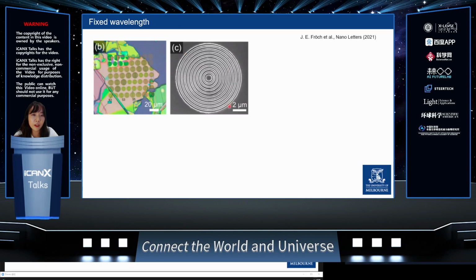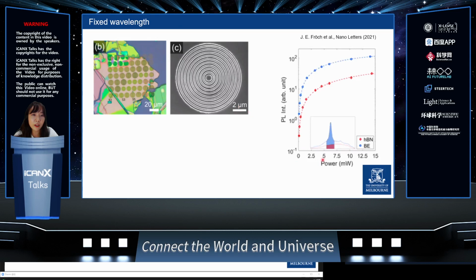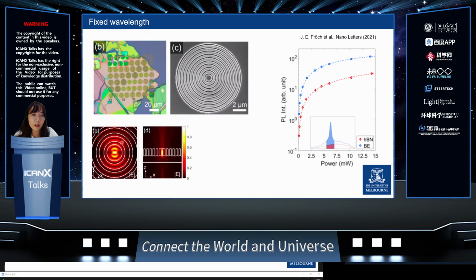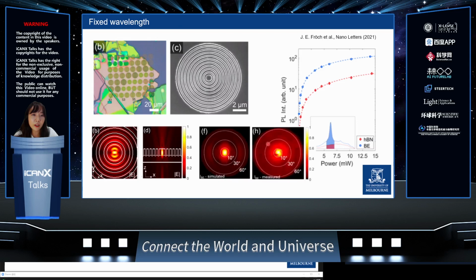After nanofabrication, the entire sample was homogeneously irradiated with a focused ion beam to generate boron vacancies. Now we compare PL intensity from the center of the bullseye cavity and outside of the cavity, and we can see PL enhancement in the blue curve. This enhancement is due to the cavity effect that increases the emitter's decay rate. This is the FDTD simulation result. In addition, the bullseye cavity has a directional cavity mode, which is seen in this cross-sectional intensity profile and also in the far field pattern. This directional emission is experimentally verified as well, as shown here.